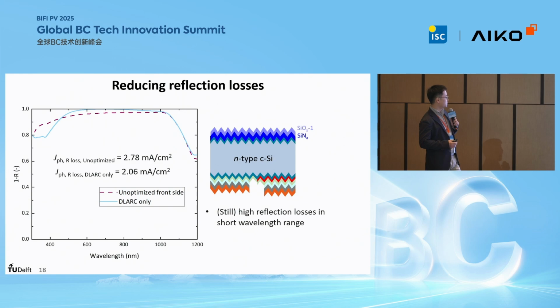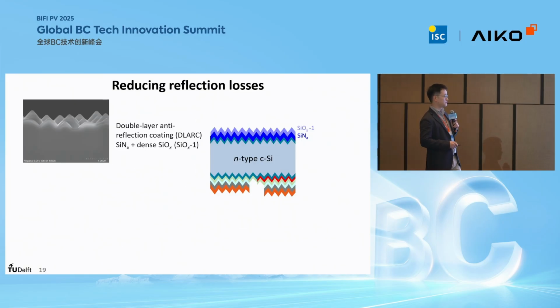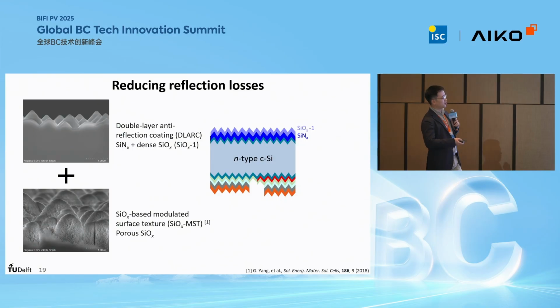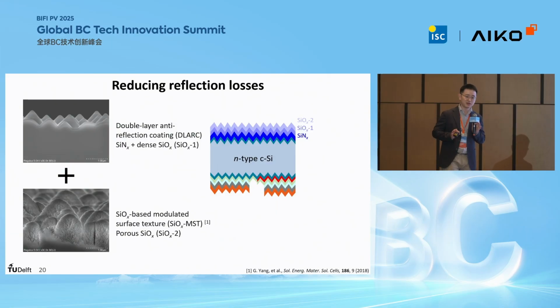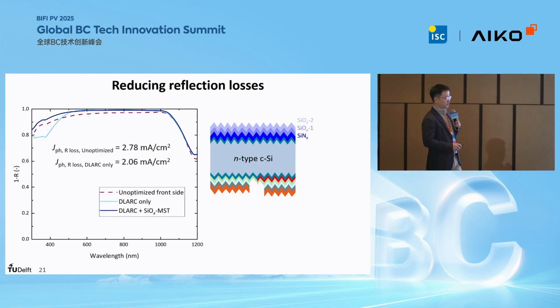However, if you look closely at the shorter wavelengths below 600 or below 500 nanometer, this device still features relatively high reflection losses in the shorter wavelength range. So to address this, on top of the double-layer anti-reflecting coating, we added a porous silicon oxide layer that is formed via a plasma and then treated with some HF etching afterwards. With such a structure, we could have better minimized reflection loss in the shorter wavelength range. And this leads to even further reduced total reflection loss to 1.76 milliamp per square centimeter.